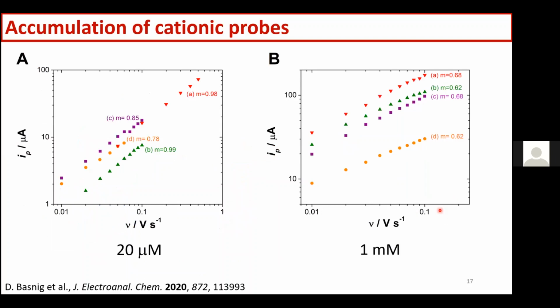Just to show also the adsorption, here we plotted the peak current as a function of the scan rate in logarithmic scale, and a slope of 1 would correspond to that adsorption behavior, and a slope of 0.5 would correspond to a diffusion profile. You could see that for the paraquat and the diquat, we reach a slope of 1, and for the ruthenium hexamine and the ruthenium tris-bipyridine, we were in a mixed signal there for 20 micromolar. Then when we increased to 1 millimolar, as I showed you before, for paraquat, everything is a mixed diffusion adsorption behavior.